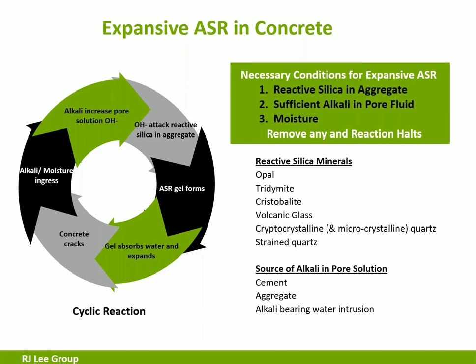Once you have that, alkali starts attacking the aggregate, and you form an alkali silica gel. That gel expands with water and cracks the concrete, and once you have the cracking, it allows more moisture to come in and start the process over and over. So it really is a cyclic reaction.